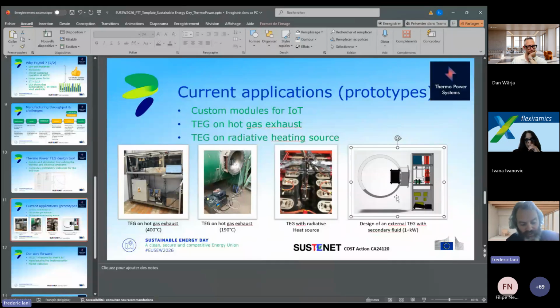There's something I wanted to say to compare with, for instance, photovoltaic. You see here on the right a big gas exhaust pipe. In there, you have a small exchanger. Of course, we will maximize the exchange surface, but we capture only a fraction of the available heat. Then from the captured fraction, we convert a fraction. So the total efficiency is very low. We cannot say that the efficiencies are fantastic, but it's a low efficiency on a big quantity of heat, and in the end, it's at a very low cost. So that's a game changer. You can always retrieve this heat.